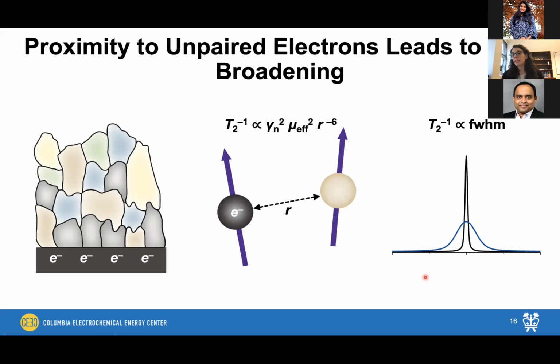So if we think about something like lithium carbonate, which would normally give a very sharp line shape in NMR, like this black line that I'm showing here, when we put it near an electron, all of a sudden, its T2 is going to become very short, and it's going to give a very broad NMR line shape, like this blue line that I'm showing here.